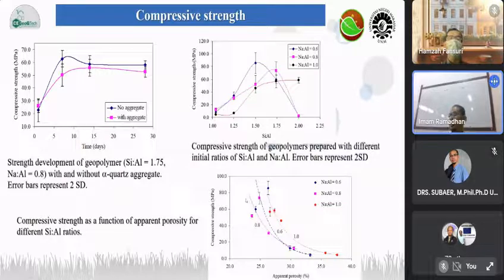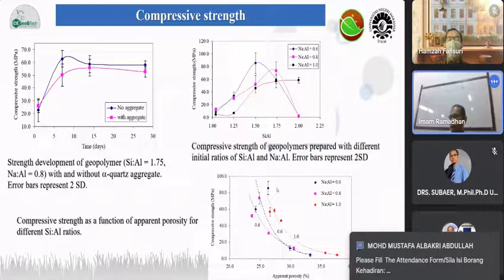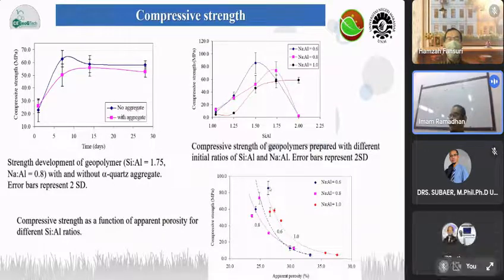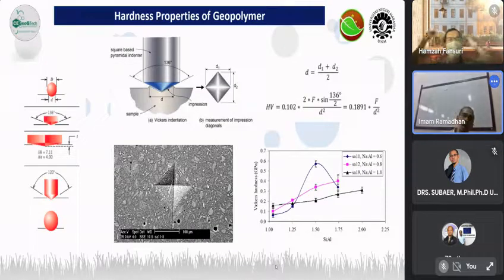The best compressive strength that I could produce at that time is almost 90 megapascals, by using small samples of 5 centimeters in height and 2.5 centimeters in diameter. I got around 90 megapascals with porosity between 26-27%. So that's the relationship between the physical and then mechanical properties of geopolymer. Now let's move quite quickly.